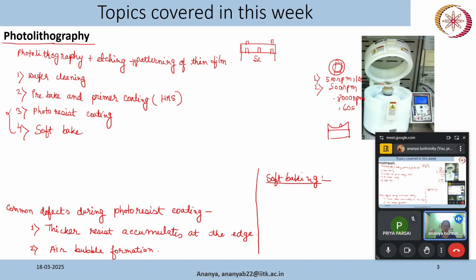Also, proper soft baking is important, because after soft baking we will have a uniform photoresist layer with uniform optical properties. If we don't do this process properly, we will have a material with different optical properties, which may change the resolution and other things during the photolithography process. So we look at the data sheet of the photoresist that we are using, and whatever process is mentioned there, whether it is 90 degrees Celsius for 1 minute or 100 degrees Celsius for 1 minute, we will follow that.